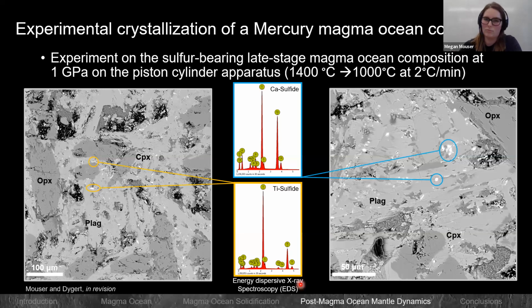So we thought we were going to just pretty much crystallize calcium sulfide. That's kind of what we anticipated with this. And probably about 75% of what I identified was calcium sulfide. But what was interesting is that the other 25% or so of the sulfides that I identified were actually this titanium bearing sulfide, which I thought was pretty interesting.